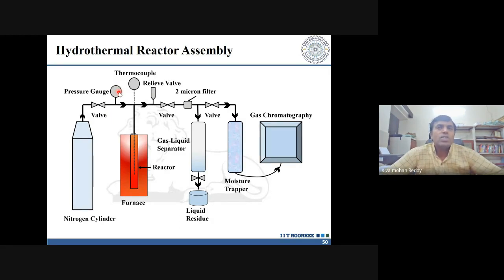Now the operating conditions are beyond the critical point of water, that is 22.1 megapascal and 373 degrees centigrade, since we are operating at 600 degrees centigrade. Then we allow the reactor to stay at those operating conditions for a specific period of time, which is called the residence time. Once the residence time is completed, we open the outlet valve. As soon as the outlet valve is open, the product mixture passes through a 2-micron filter to make sure that no particulate matter enters your gas phase analysis system.